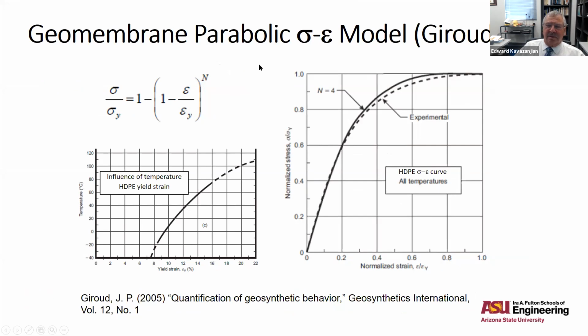of geosynthetic materials, where he developed this parabolic stress strain curve for HDPE geomembranes before yield, actually for any geomembrane. And the behavior is a function of the exponent N. And for HDPE, that N is equal to 4. And he's also able to capture the effect of temperature based upon its effect on yield stress. So the stress strain curve is normalized with respect to the yield stress and the yield strain.